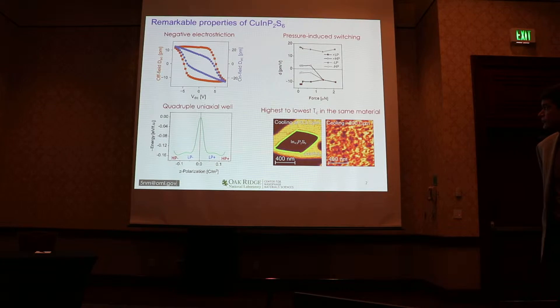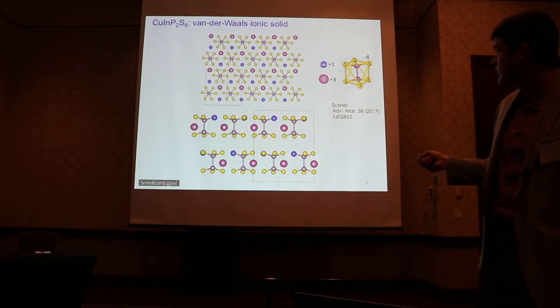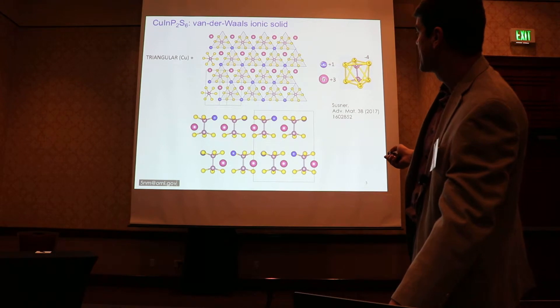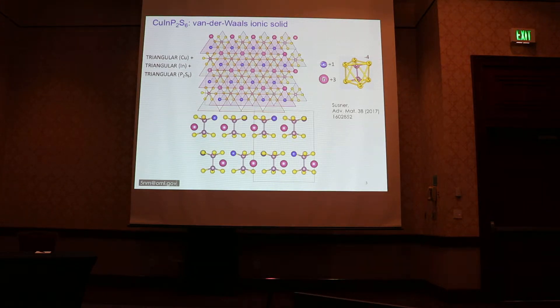Let's take a look. First, an introduction to the material itself. This is a layered Van der Waals solid and on first glance it looks a little complicated, but if we enumerate the lattices, things become pretty clear. Looking from the top on a single layer, we have coexistence of three triangular lattices: the first cation, copper; a second cation, indium; and a third composite anion, P₂S₆⁴⁻. This is one triangular lattice more than you find in graphene and TMDs — a step up in complexity.